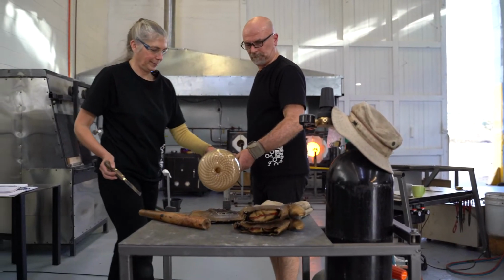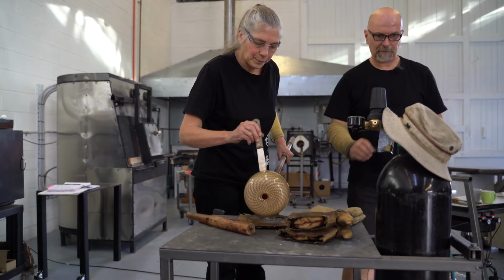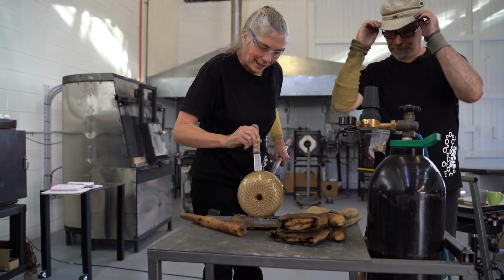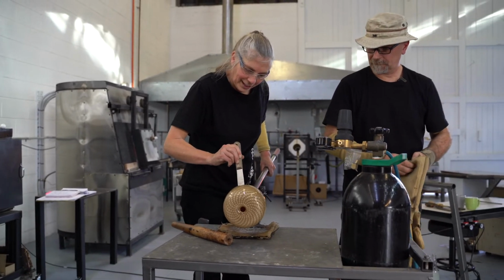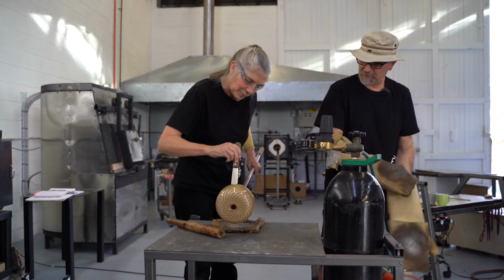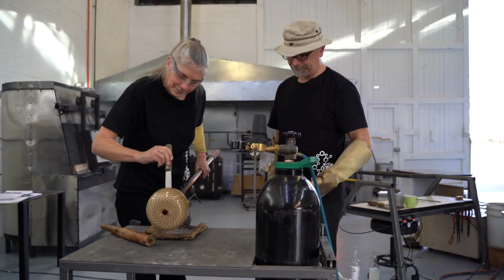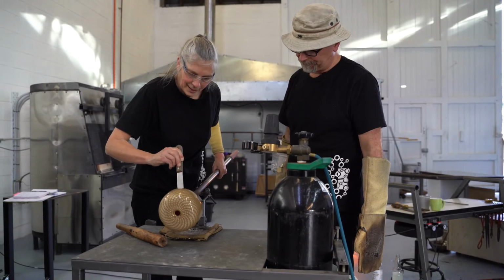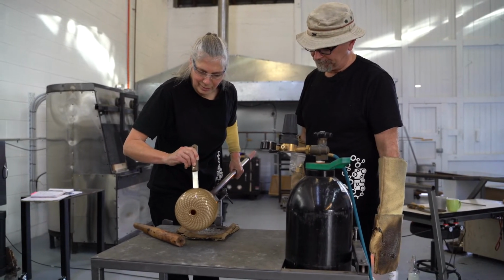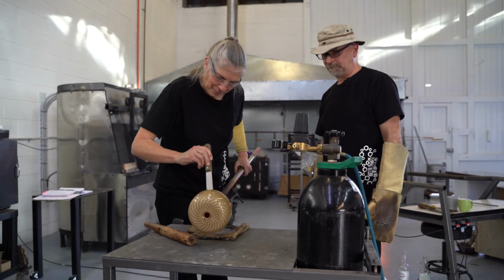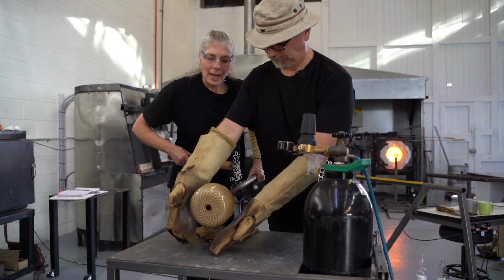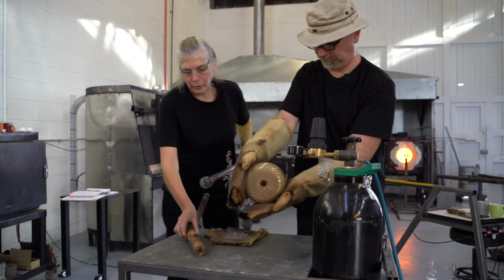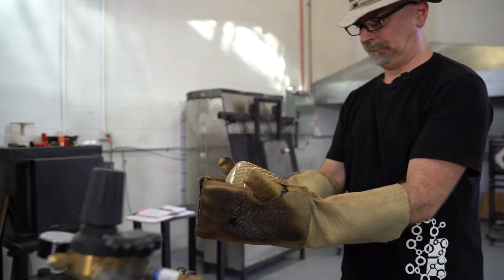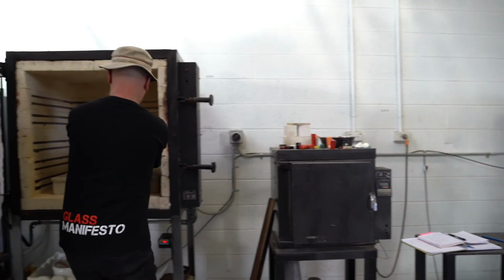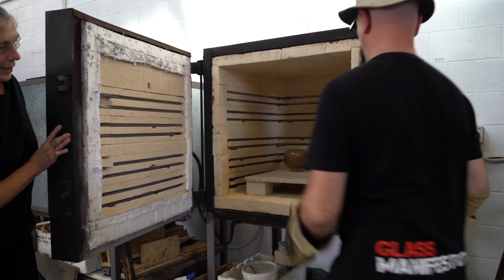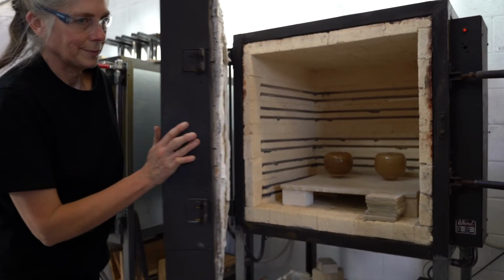The annealing temperature starts at about 510 degrees, and will actually hold all of the work throughout the day at 510, and then it cools down to 400 degrees centigrade between 24 and 36 hours, and then it can progress a little bit faster down to room temperature from there on. And that's just to remove the stress from the glass. As it's cooled from a liquid to a solid, there's a lot of inherent stress in the clear glass, but also between the layers of all the colours. So this cooling phase is a critical part of the process as it removes all of that stress and strain within the piece.